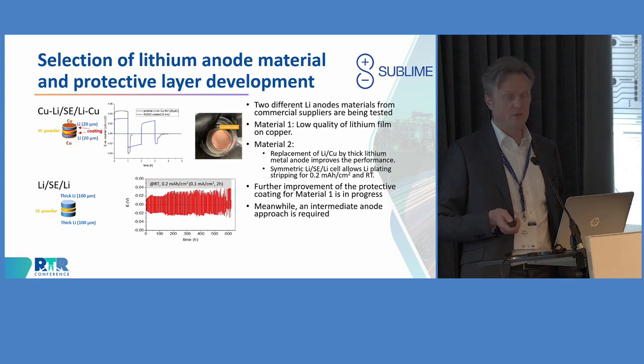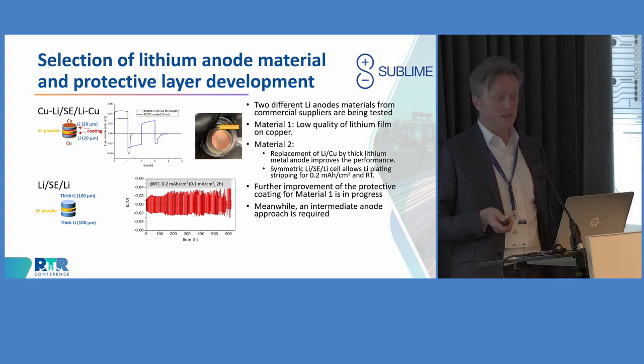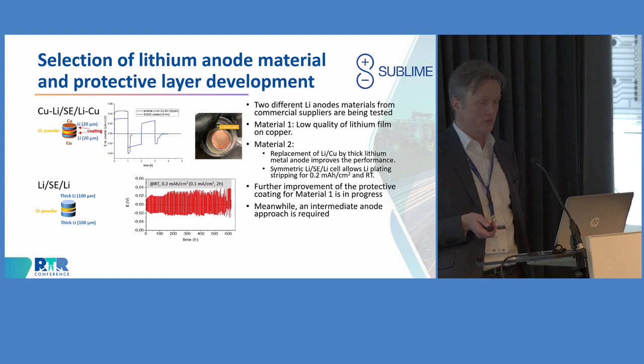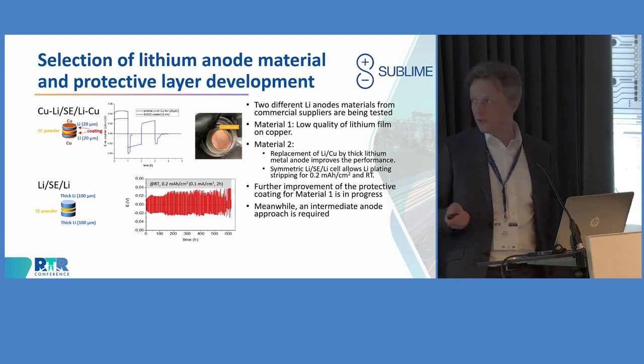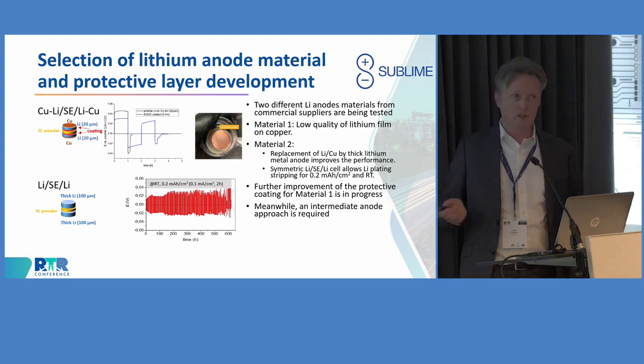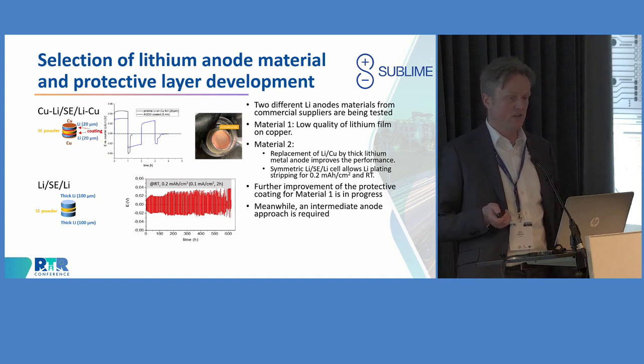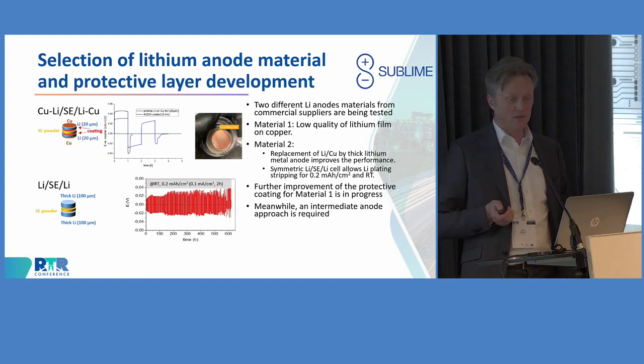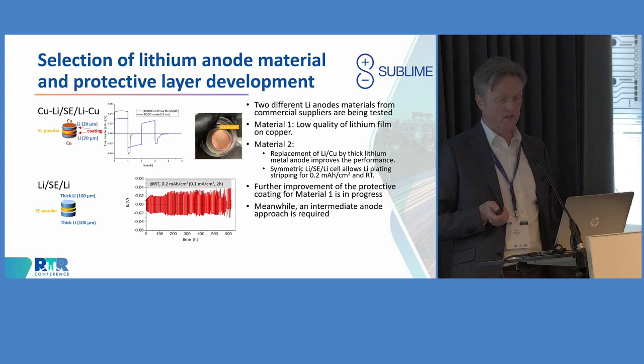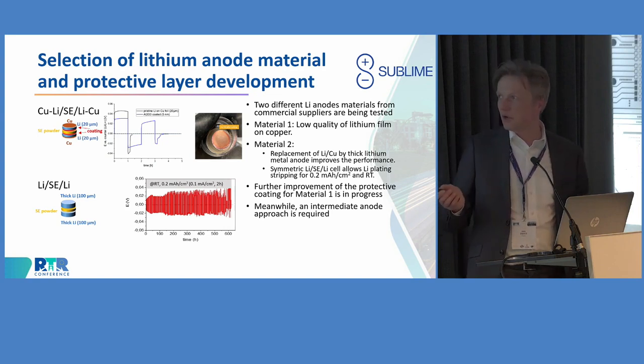We are doing tests of these, and we have different materials available. And this is something where we found the first challenges. For example, the first material, which in principle we need in order to really reach the very high energy densities that we are targeting, that's very thin lithium on copper. That seems to be kind of low quality at the moment.